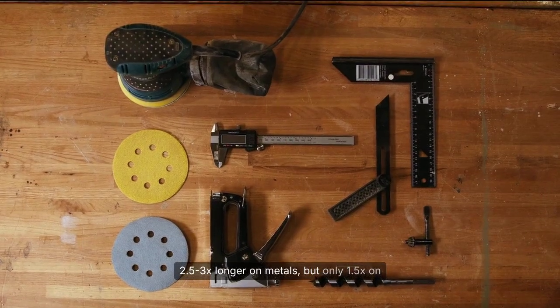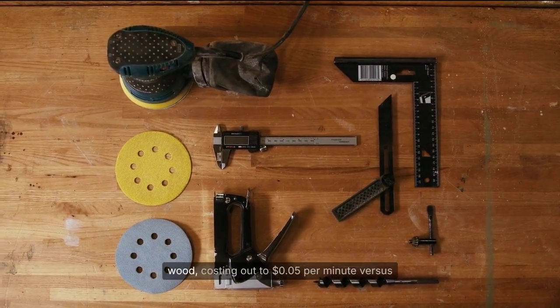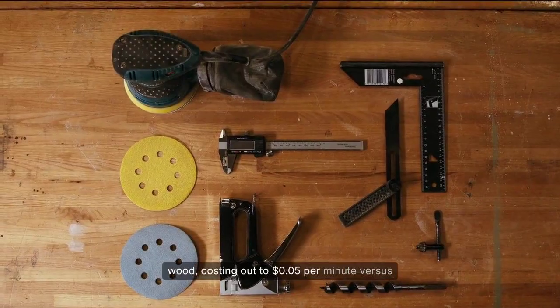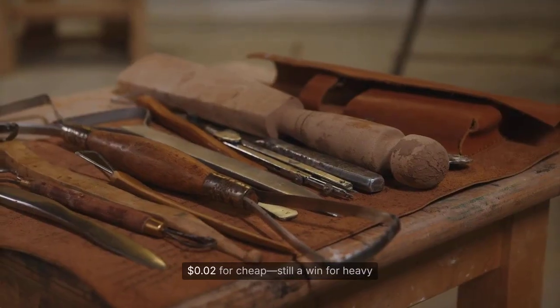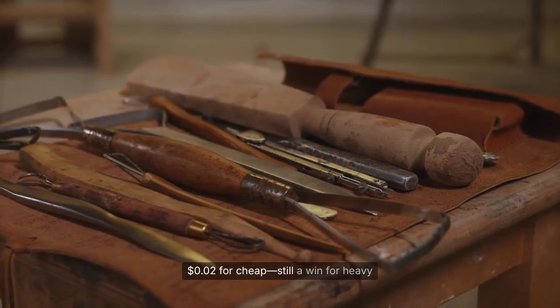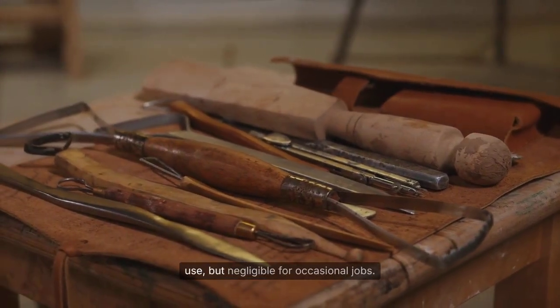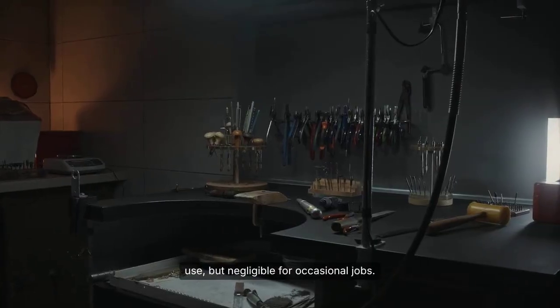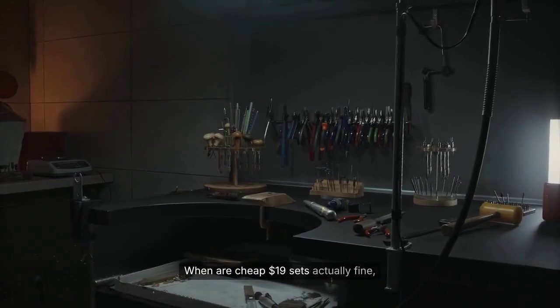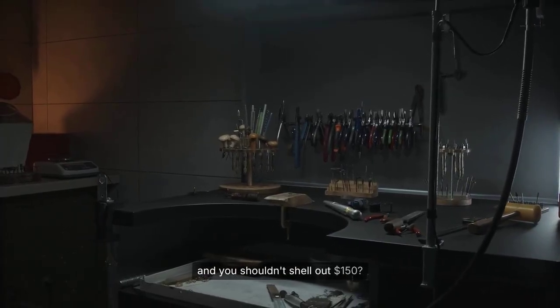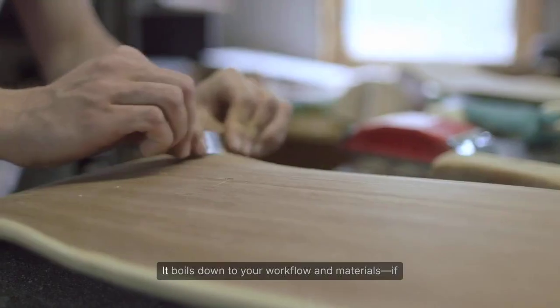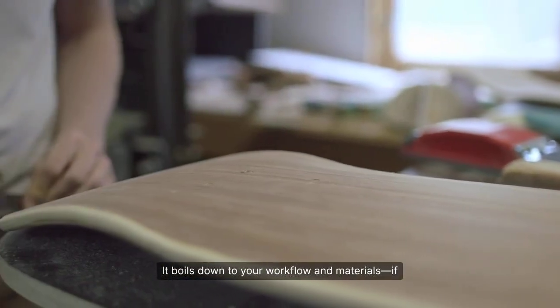Across 10 runs per set, premiums lasted 2.5 to 3 times longer on metals, but only 1.5 times on wood, costing out to $0.05 per minute versus $0.02 for cheap. Still a win for heavy use, but negligible for occasional jobs. When are cheap $19 sets actually fine, and you shouldn't shell out $150? It boils down to your workflow and materials.